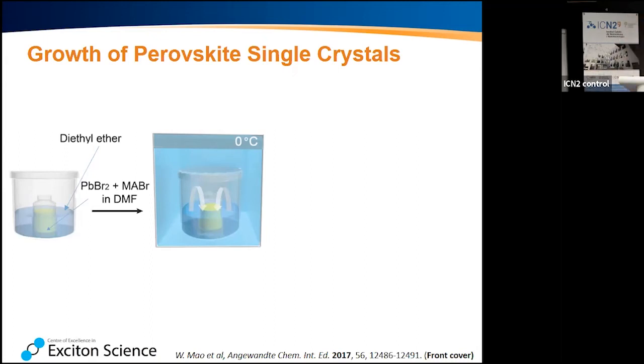So you have a jar in here where you will have the precursors for your perovskite. Around it, you place that in a jar that has ether all around it. Now, if you put a lid on and you put it away, you don't look at it, and you come back after a while, you realize that the ether will slowly diffuse into your precursor solution. Your perovskite itself becomes very insoluble in ether mixtures with other solvents. And what you generally get is you get the beautiful perovskite crystals come out.